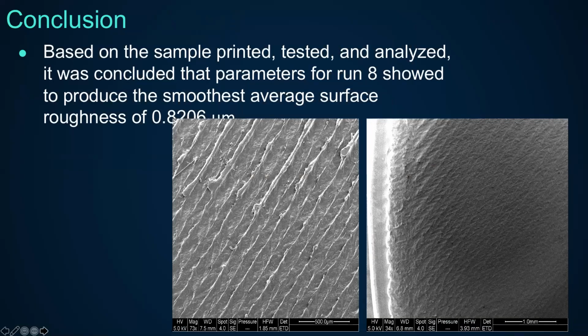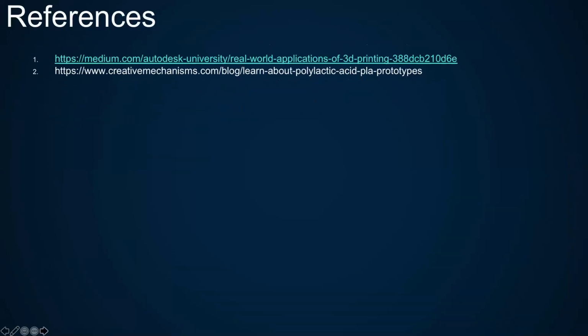So based on what we printed, tested, and analyzed, we were able to conclude that the parameters for run 8 showed to produce the smoothest average surface roughness of 0.8206 micrometers. And in comparison, again, the picture on the left is run 6 and the picture on the right is run 8. I would like to thank all my mentors, my undergraduate mentors, and Dr. Matthew Caputo for teaching me everything I could learn about 3D printing. Thank you.